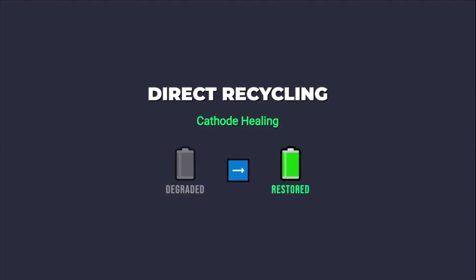Direct recycling bypasses the destructive chemical steps of hydrometallurgy and pyrometallurgy. The goal is to preserve the valuable crystal structure of the cathode material. This method involves physical separation, followed by a process called cathode healing or relithiation. The spent cathode material is treated with a lithium source, such as lithium hydroxide, and subjected to high-temperature annealing, typically between 800 and 1,000 degrees Celsius.